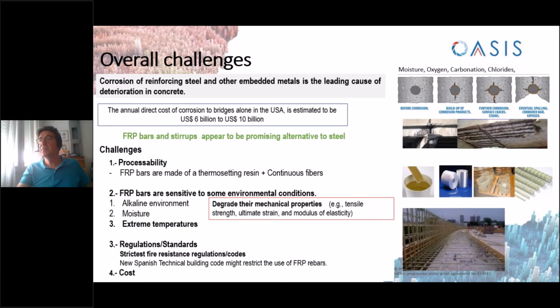From our experience, fiber-reinforced polymer rebars are one of the best alternatives to steel rebars, and in many countries, conventional steel rebars are slowly being replaced by fiber-reinforced rebars in very specific projects due to their high strength-to-weight ratio, corrosion resistance, durability, and better stiffness than conventional steel rebars. However, the use of fiber-reinforced polymer rebars still presents many challenges regarding processability, inline quality control, and long-term durability in very aggressive environments. Also, the newer, stricter regulations and standards are a problem for existing fiber-reinforced polymer rebars, as is the higher cost of composite rebars compared to steel rebars.